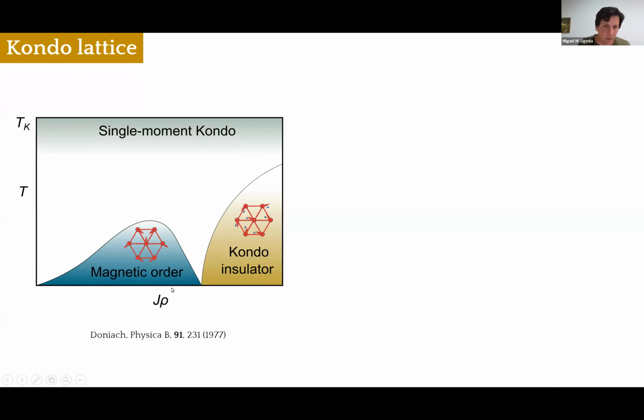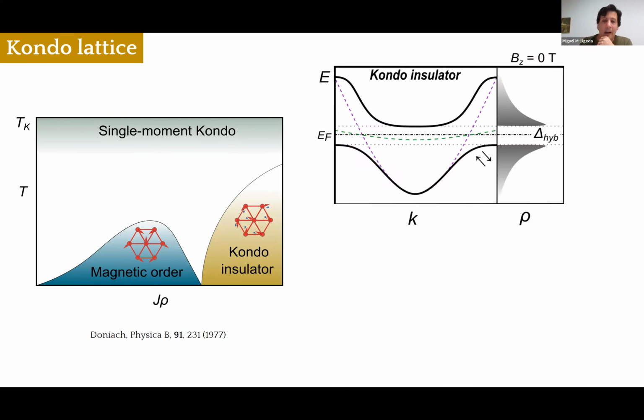So for example, if the strength of this coupling is relatively weak, then the system will prefer to show a magnetic order with some spin interactions mediated by the substrate, the RKKY interactions. However, if we continue to increase this coupling, for a certain critical value the system prefers to become a paramagnet and all these spins will be fully screened by the conduction electrons, which is called the Kondo insulator regime. So what we have done is to study these two ground states in terms of the density of states, which is what we measure with STM.